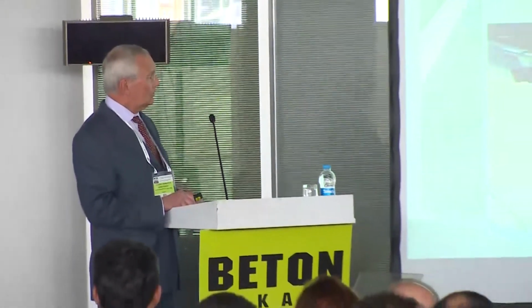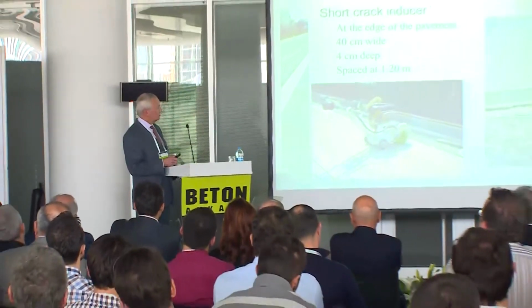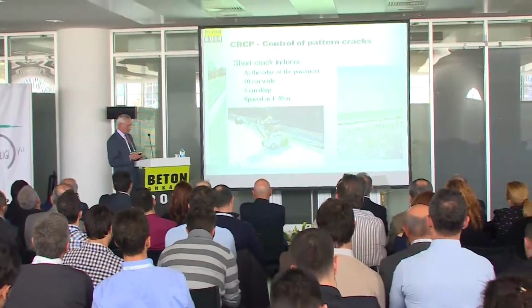Another experiment, short crack inducer, also in CRCP, at the edge of the pavement, 40 centimeters wide, 4 centimeters deep, and spaced at 1.20 meters. It's to control the distance between the cracks.